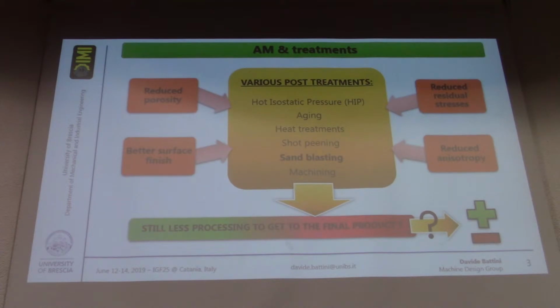So we actually analyzed sandblasted specimens, since one of the problems of as-built additive manufactured specimens is that they usually don't have that grade of fatigue strength. And sandblasting is quite cheap, and it should be effective.